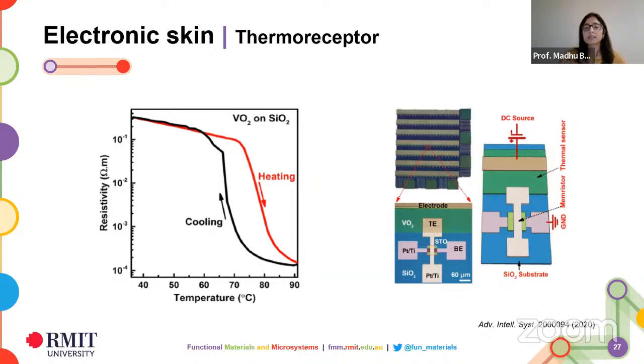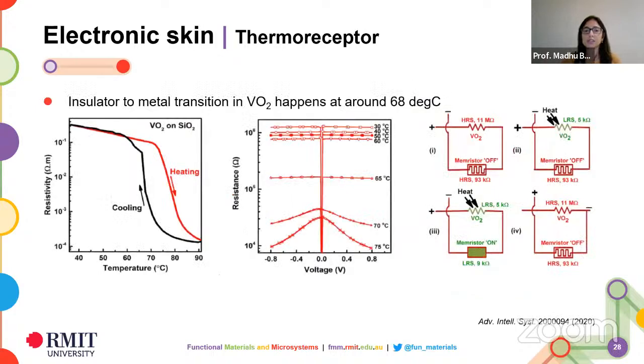Now, vanadium dioxide is a fascinating material because it's a phase change material. What happens when you heat up vanadium dioxide is that beyond a particular temperature of around 65 degrees centigrade, it goes from being an insulator to a conductor. You can see the resistivity of the material significantly drops once it reaches a phase change temperature of 67 degrees. And once you cool it down, it goes back to being an insulator at room temperature. So it has this fascinating property of changing from an insulator to a conductor, and that's the property we used to mimic the thermoreceptive characteristics of the skin.